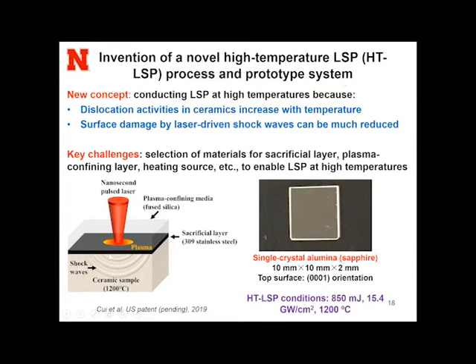And here shows a diagram of our experiments. We use the stainless steel coating as a sacrificial layer. And finally we chose fused silica as a good material for plasma confining media. And here I would like to talk about some work we did on the single crystal alumina sapphire. And recently, we also have been successful in the silicon carbide polycrystal ceramics using the high temperature laser shock peening process.